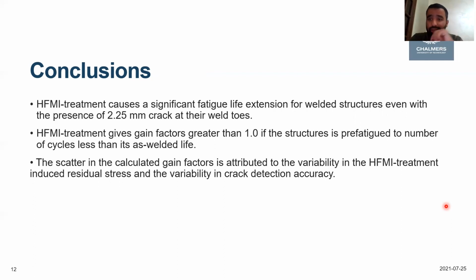And finally, we can say that the scatter in the calculated gain factor is related to the variability in the introduced residual stress and also the crack detection accuracy.